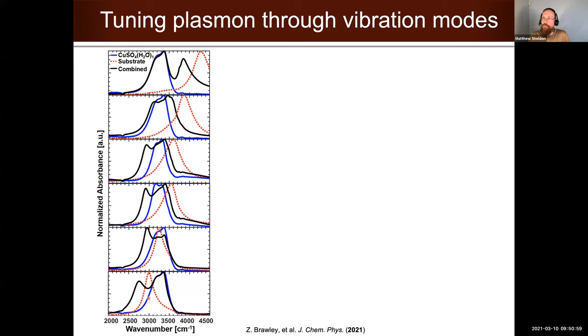The black curves, if I take you back up to the top, are the actual spectrum we measure over the array when the salt was deposited. And as you can see here, I hope, this plasmonic resonance peak position has redshifted in this particular case, as you see in this black curve, because of the refractive index change. The salt is changing the refractive index, which also changes the resonance of the plasmonic mode. But nonetheless, in this particular spectrum, you can see that the mode of the plasmonic substrate is primarily preserved as it was before. The magnitude has gone down a little bit, but I can talk about that in a sec. And the spectral shape and the features that we can associate with the salt are also approximately unchanged. This is because we are clearly very much out of resonance.